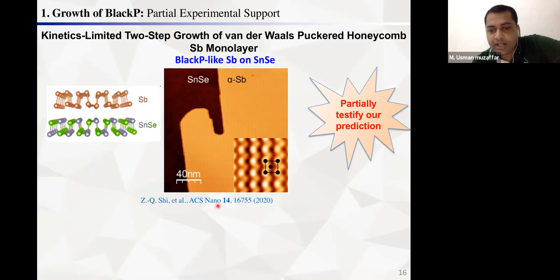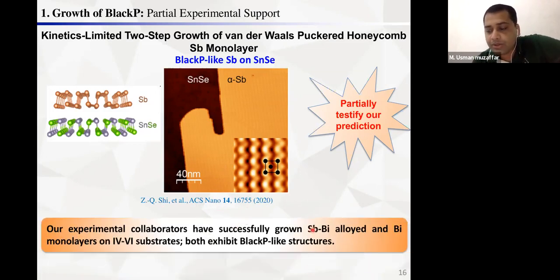It means that they further tried to identify Sb, and further confirmed it by synthesizing the Sb and Bi monolayers, the alloyed monolayer, and the bismuth monolayers on a group of IV-VI substrates. So it means that the idea we have given is not specific to a single element. It may be valid for other systems as well. So our idea is partially supported by the experiments. Partially means that we did the calculation for black phosphorene. They are still trying to grow the black phosphorene, but in the meanwhile they got the Sb phase. So this idea is partially supported by the experiments. So hopefully the black phosphorene will also grow.